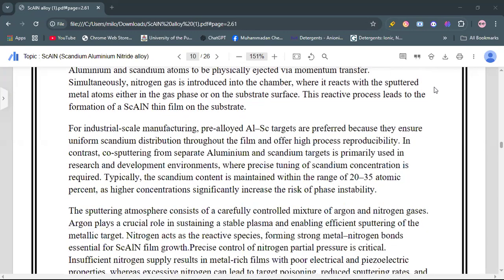For industrial scale manufacturing, pre-alloyed scandium aluminum targets are preferred because they ensure uniform scandium distribution throughout the film and offer high process reproducibility. In contrast, co-sputtering from separate aluminum and scandium targets is primarily used in research and development environments where precise tuning of scandium concentration is required. Typically, the scandium content is maintained within the range of 20 to 35 atomic percent, as high concentrations significantly increase the risk of phase instability.